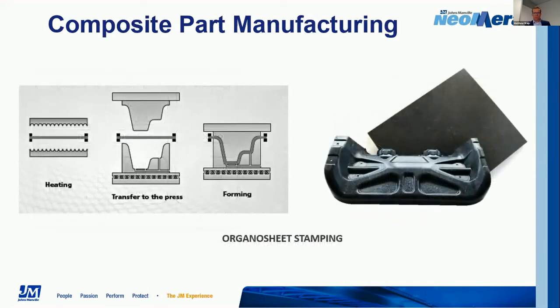The other side is what we would consider more generally as Organosheet stamping. I think there's a lot of subcategories of process here: thermoforming, compression molding, and here you're taking a sheet product of some kind, you're heating it up, and it's going in a mold like you would in a traditional metal stamping process. And you know, again, you just have the preheat step. This is a common process for people today as well, even on the sheet metal side. If you're familiar with hot stamping, this is essentially hot stamping for thermoplastics, but just at a much lower temperature. And then you get the benefits of a very viscous system when you're trying to form the part. You can create quite unique and intricate shapes.